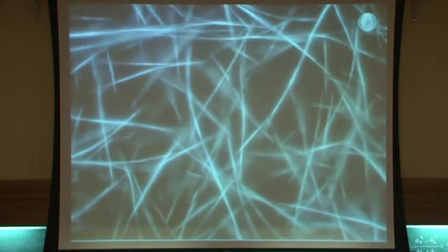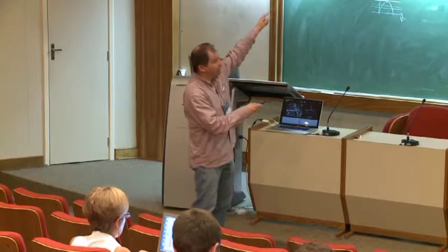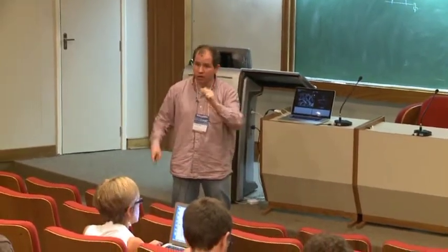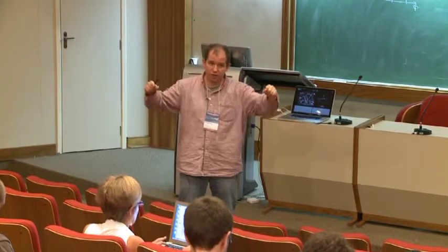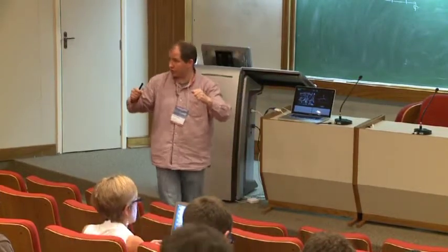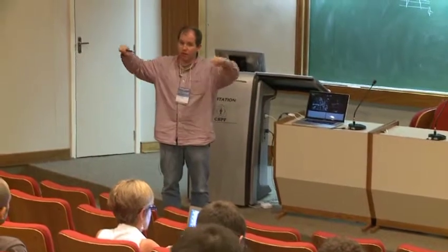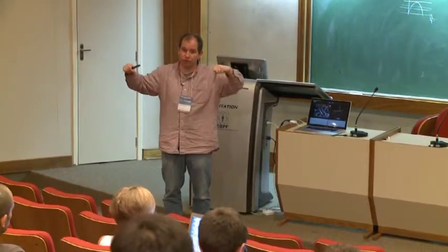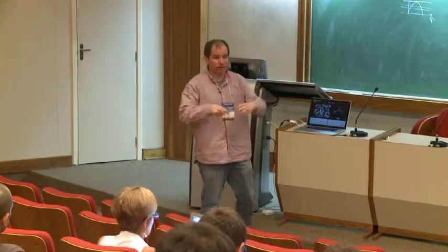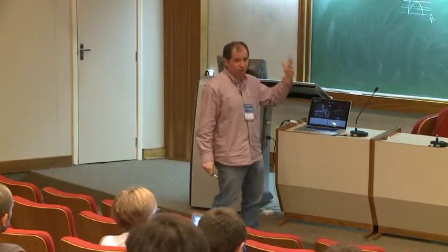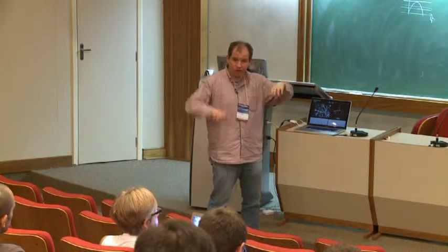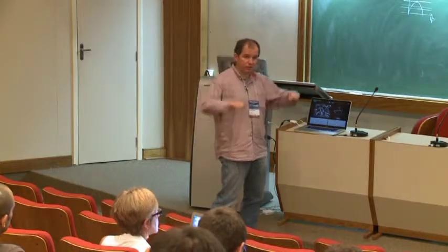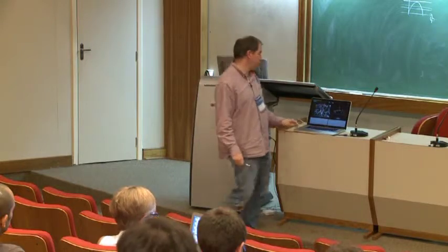What's important to mention is that this length scale is 100 microns. Our single microtubule is 1 micron long, right? So what you're breaking when you fracture this is not individual microtubules, you're really breaking this composite microtubule bundle that's held together with very soft depletion forces. That's why we started studying those frictional properties, because we want to understand the buckling behavior of a composite bundle instead of a single beam, which has been studied extensively.